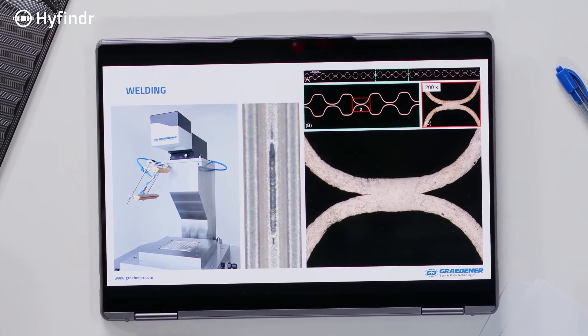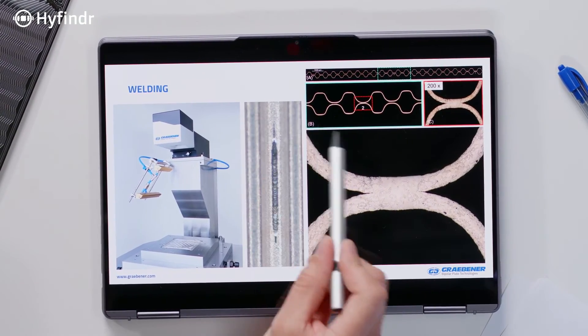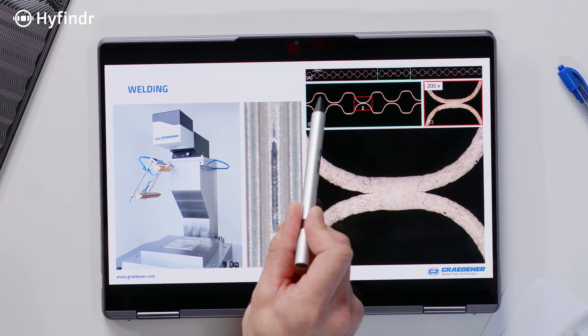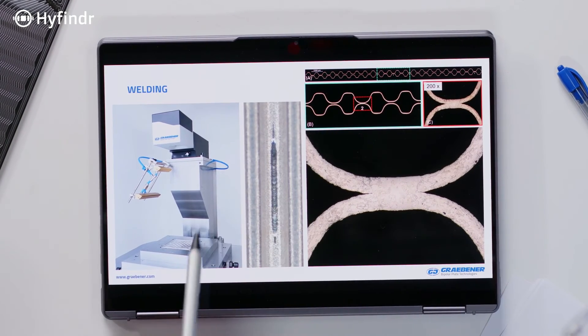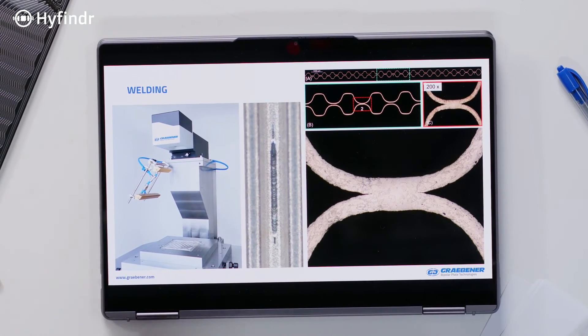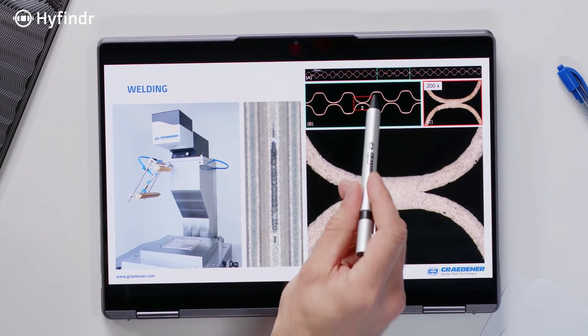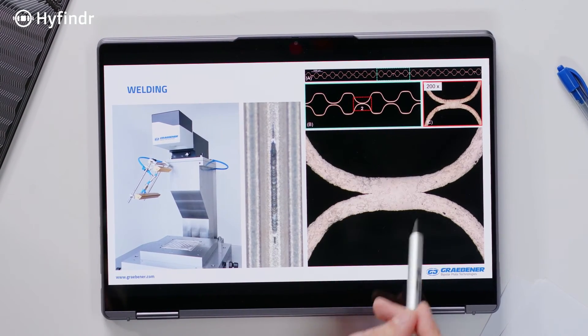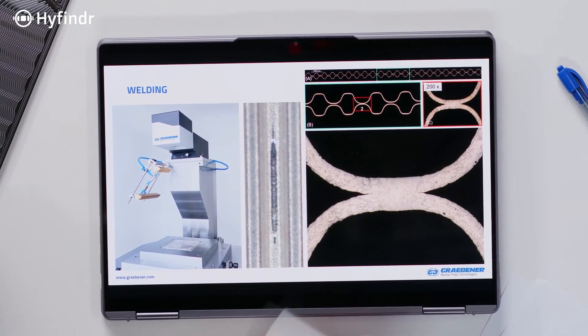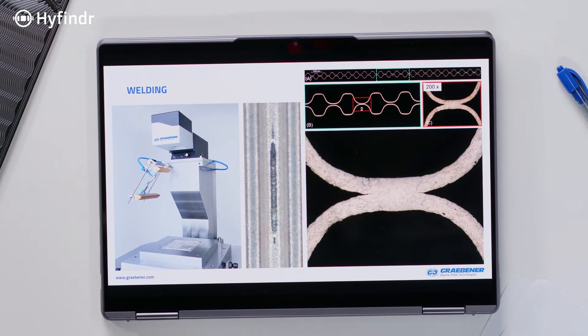You can see here the small gap between the blades. This gap needs to be as small as possible, because what the laser does is melt this area and bring the two materials together. This is why the laser welding process is the most critical process in the production line.